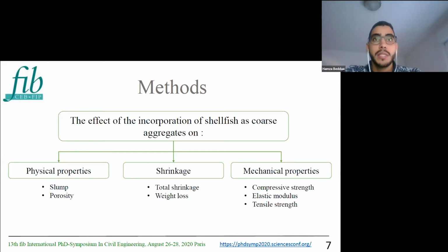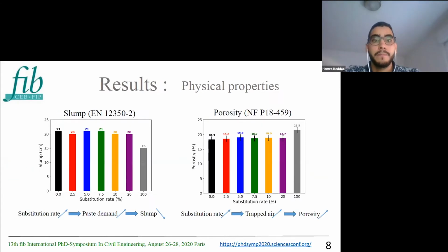The properties studied for these concretes are slump, porosity, drying shrinkage, and weight loss. Regarding mechanical properties, compressive strength, elastic modulus, and tensile strength by splitting are also measured. So we will start with the results of the physical properties.